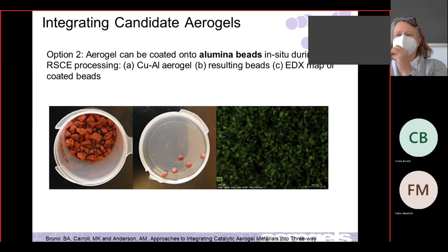And we can. You can see there's some alumina beads in here. This is a copper alumina aerogel. We did RSCE processing, all of it in there. Here are the beads, and here's an EDX picture of a bead showing that, sure enough, we coated it with copper, so we could do it that way too.